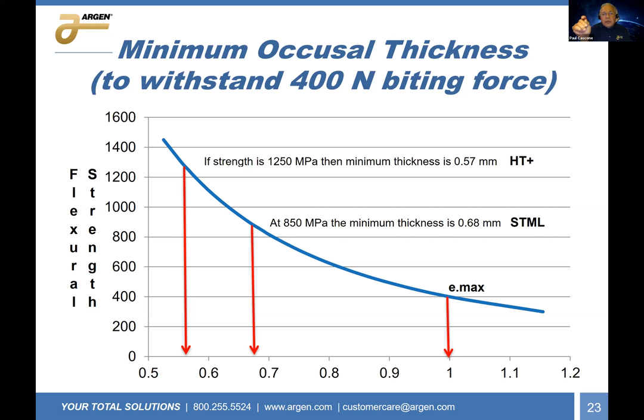It gives you more insurance, I should say. Most of the 3Y materials are about 1100 megapascals. Our HT plus is a little higher than that, so we can go a little lower in thickness.